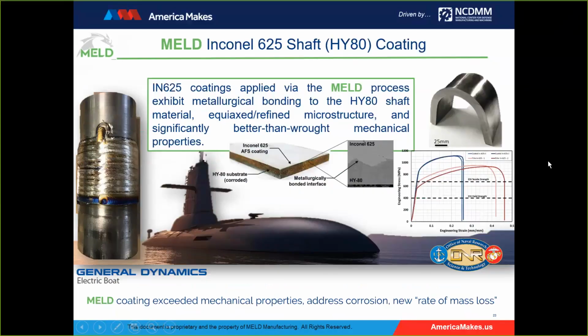So we got engaged with a Navy submarine propeller shaft made out of HY80. It's coated with Inconel 625 for wear resistance. I'll start off with a sample that was corroded. You just saw this on the other slide. We immediately deposited with no preparation, fully dense, which to us means no voids or no porosity. We have eliminated any pathway for corrosion to work back to the surface. So I'm emphasizing here how we handle corrosion: in this coating application, there's no vehicle or pathway for the corrosion to work back to the surface.